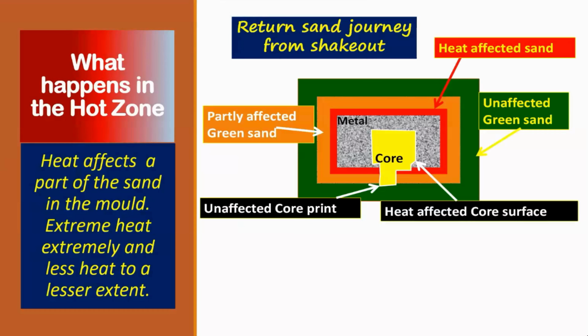You will see inside a mold. The green part is a mold, and this part is a casting. Metal is a casting, and then you put a core inside, and you see that when some metal is filled, hot metal is filled, then there is a zone which is heat affected, extreme heat. And next to it, we have this partially affected green sand. And behind this, a portion of the green sand which is not affected at all. It is much beyond the hot zone.